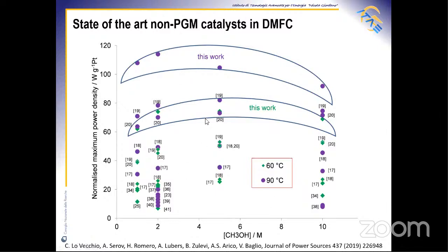As observed, the present catalyst shows the highest performance until now reached with the non-PGM catalyst in direct methanol fuel cells, both at 60 degrees centigrade and 90 degrees centigrade. In particular, at this latter temperature, the normalized maximum power density was ranging between 95 and 110 watt per gram of platinum, significantly higher compared to previous catalysts, also prepared by using the same methodology, but employing different precursors.